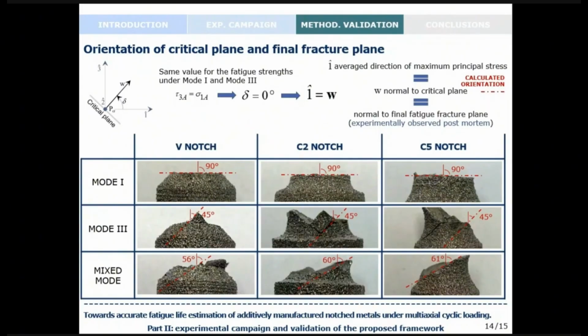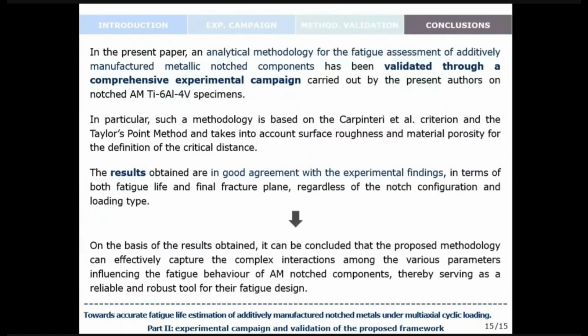configurations, whereas in mixed mode loading, we found an orientation equal to 56 degrees for V-notch, 60 degrees for C2, and 61 degrees for C5 notches. And let me say that all these results are in good agreement with the experimental observation of the final fracture plane of the specimens. So let us move to the conclusions.